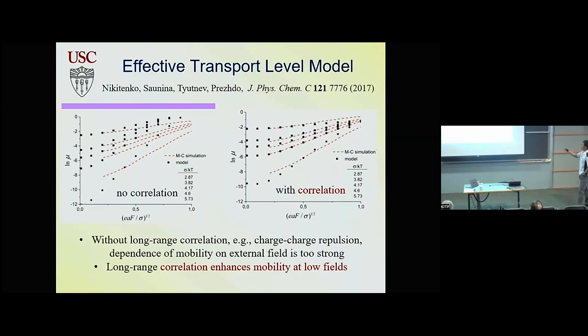So what happened in this paper, we showed that to be able to describe mobility at low applied fields, you have to build in correlations. Basically you have an electron that has to detrap, and then you have another electron that's going to move. If you include correlation between those two electrons, because one electron detraps and then pushes the other one away, you can describe the mobility in the low applied field limit that doesn't decay straight down. It has this saturation, you have more efficient mobility because of the correlation.